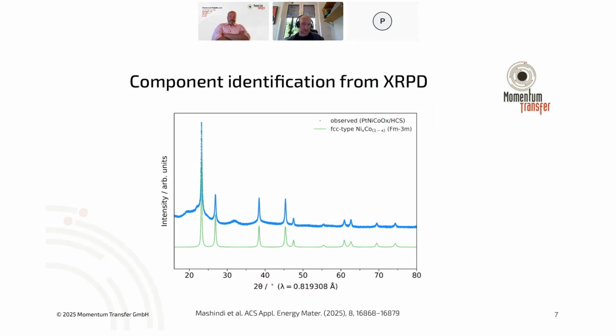And so for different crystal structures, you have completely different sets of peaks, different relative intensities. And even in cases where you have similar crystal structures with slightly different compositions, because of expansion or contraction or changes in the density of the material, you can get shifts in those peaks. So that allows you, in many cases, not all cases, to also discern different compositions as well.